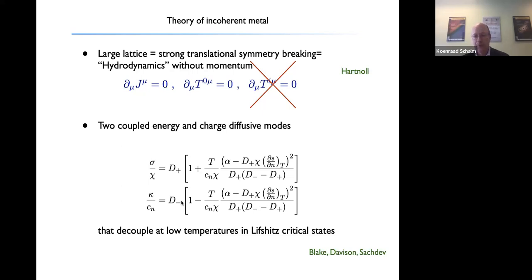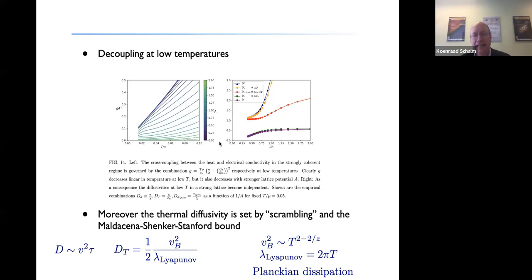Now they're coupled, but as was shown by Blake, Davison, and Sachdev, at very low temperatures in these emergent Lifshitz hyperscaling violating states, these 2 modes decouple. And you really have an independent charge transport sector and an independent heat transport sector. And the same happens, even though this analysis was done not in the presence of a lattice, it was done in the presence of large disorder, or these homogeneous lattices that you can construct in holography. We can verify that exactly the same happens in a real lattice.